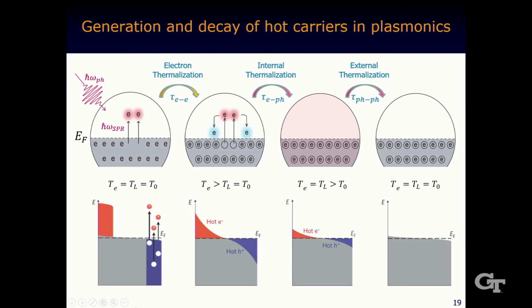And then in the next few hundred femtoseconds, the energetic electrons will exchange energy with the rest of the electrons, and eventually all the electrons will reach the thermal equilibrium at an elevated temperature. So they follow the Fermi distribution, but at a higher temperature. So in this case, we say we have a cluster of hot electrons. So that is through electron-electron scattering.